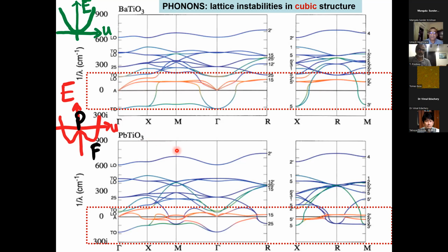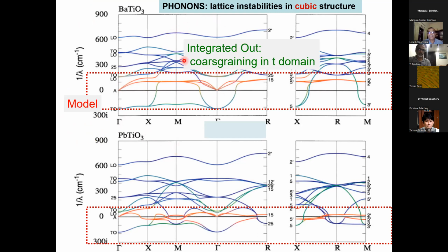So the idea is to develop a model Hamiltonian by integrating out these high energy phonons, and then the model is basically focusing on the phonons inside these red dash boxes, which involve unstable phonons as well as acoustic phonon branches here, which basically gives you the lattice distortion or deformation. Same here in lead titanate as well. So the effective model Hamiltonian is a projection of the full lattice Hamiltonian of the system into the subspace of these unstable phonons. Okay, that's the first principle we use in modeling, and this is basically the coarse graining in the time domain, because we are integrating out high frequency phonons, which means the short time scales are not so important in the phase transitions.